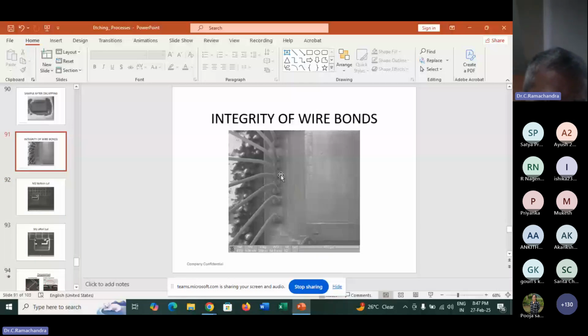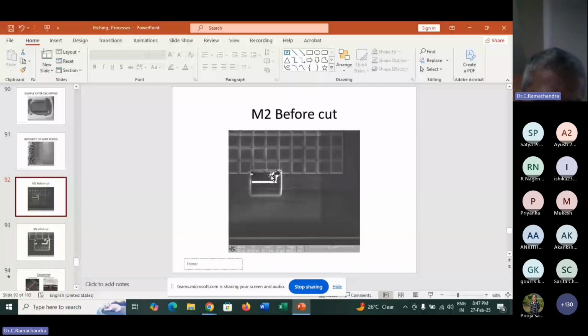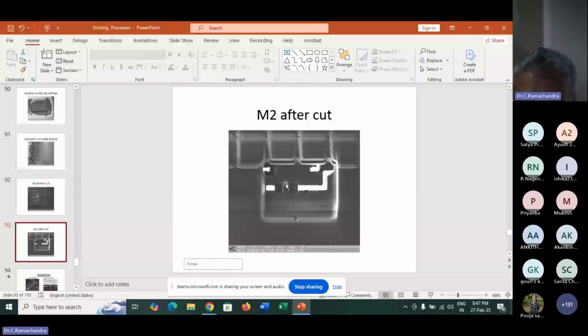So then we reach the desired metal location. We reach this location by GDS data. Then we use an ion beam to etch the material. See, the aluminum is etched here, hardly 1 micron. So now this is disconnected. After that, we tested the device and it was found to be good. So this is ion beam assisted etching.